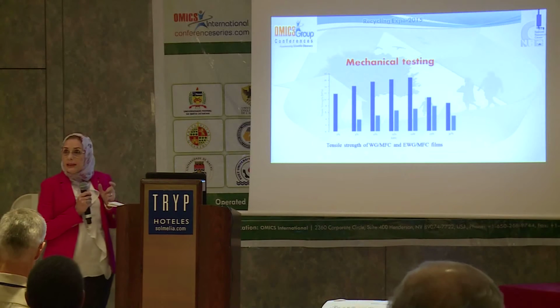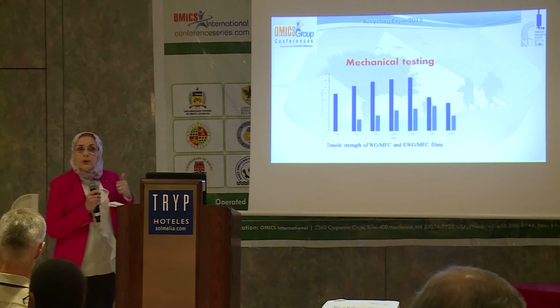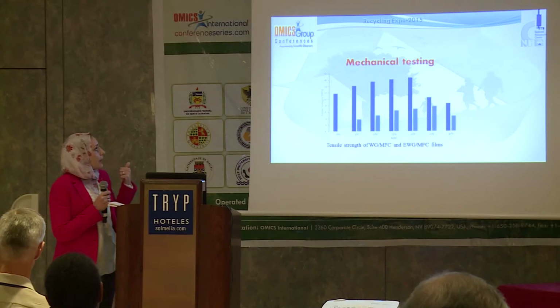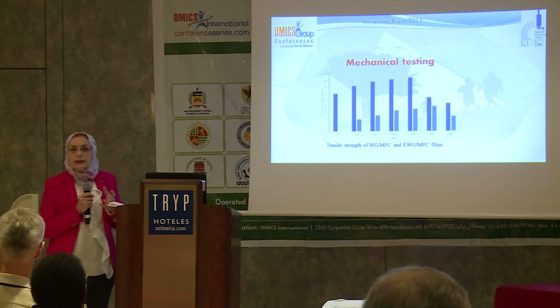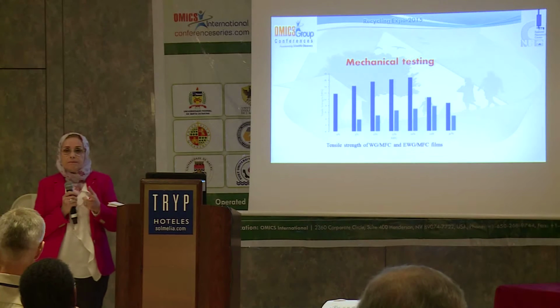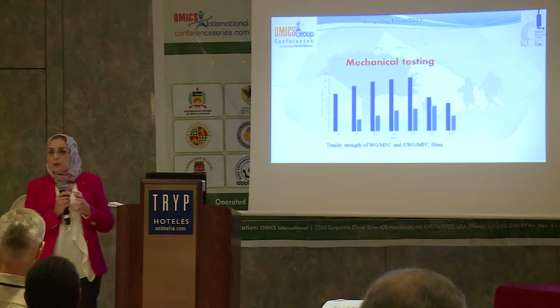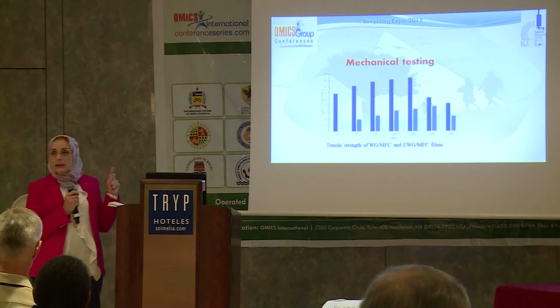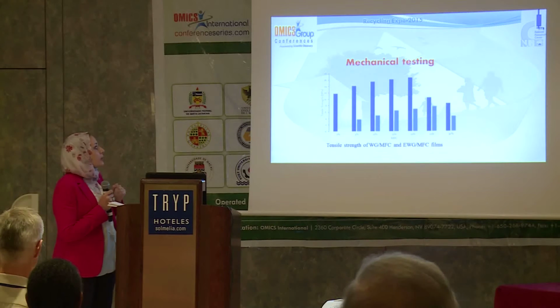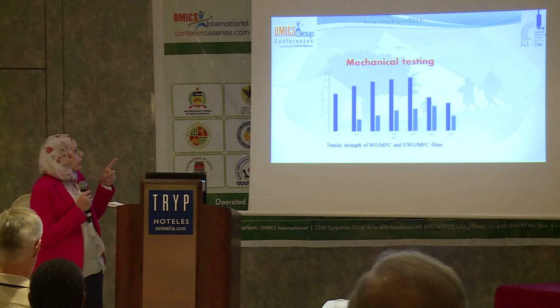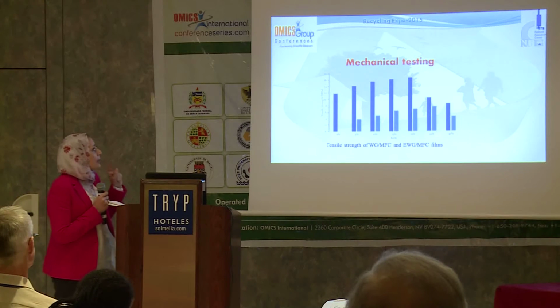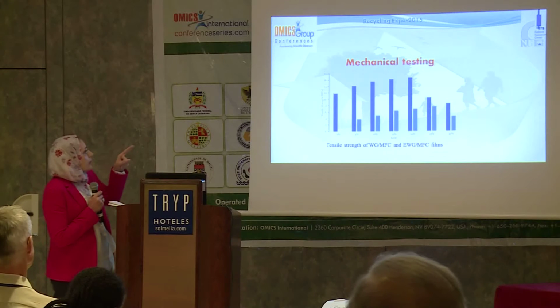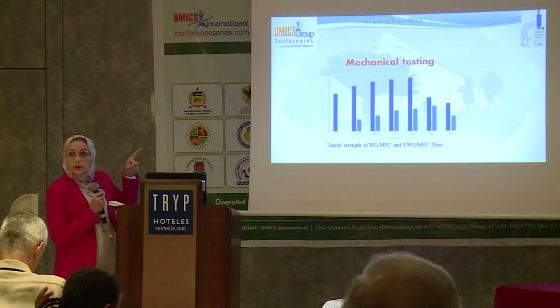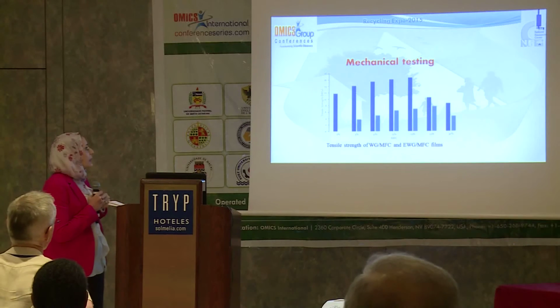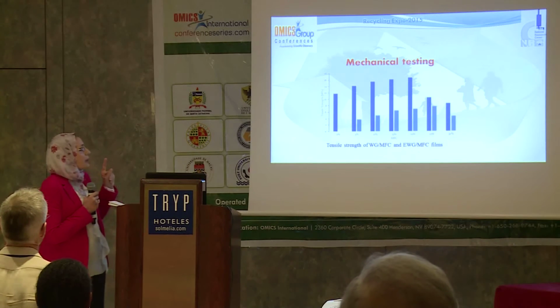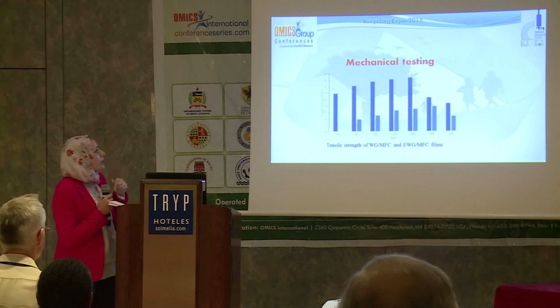Wheat gluten, which is enzymatically denatured, was filled with cellulose nanocrystals, which were used in the first part with chemical denaturation. But unfortunately, the films were loose and we didn't use cellulose nanocrystals in this study of enzymatic denaturation of wheat gluten. We used microfibrillated cellulose. Microfibrillated cellulose here filled chemically and enzymatically denatured wheat gluten. The dark blue is for the chemically denatured wheat gluten, and the pale blue for the enzymatically denatured. They were filled with percentages of microfibrillated cellulose up to 30%.